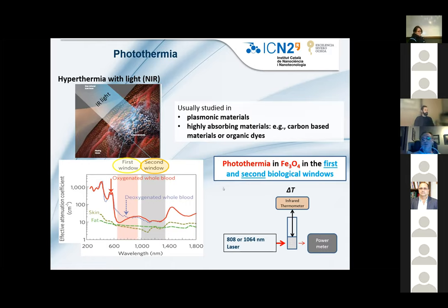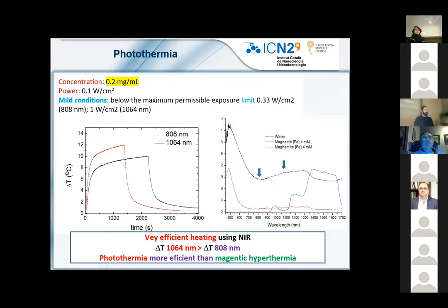So what we did was experiments at 808, which is in this area, what's called the first biological window, and at 1064, which is within the second biological window. We shine the laser at our liquid with the nanoparticles, and with an infrared thermometer, we measure the temperature. Here we use only 0.2 milligrams per milliliter and a power of 0.1 watts per square centimeter. It must be emphasized that the exposure limit for laser on the skin is about 0.33 watts per square centimeter for 808 and 1 watt per square centimeter for 1,064 nanometers. So we are far below the limit we could use.